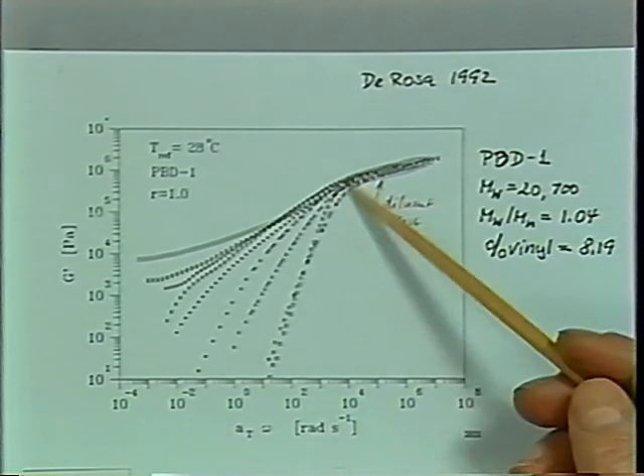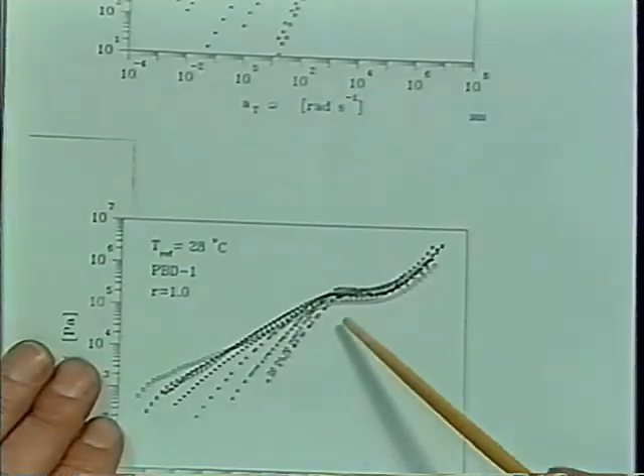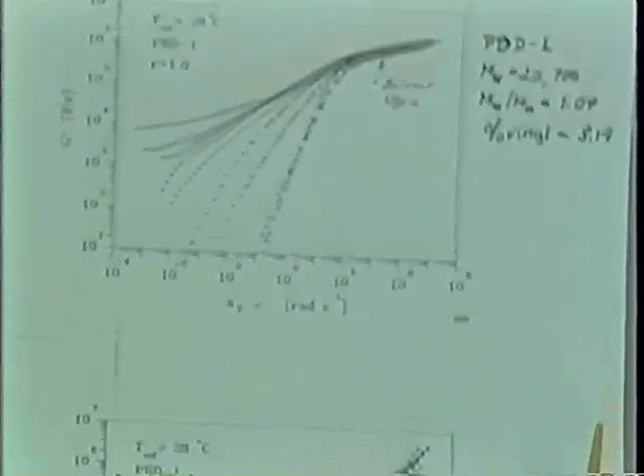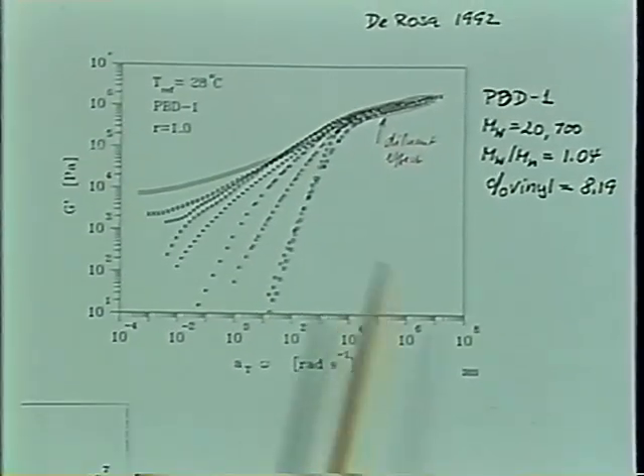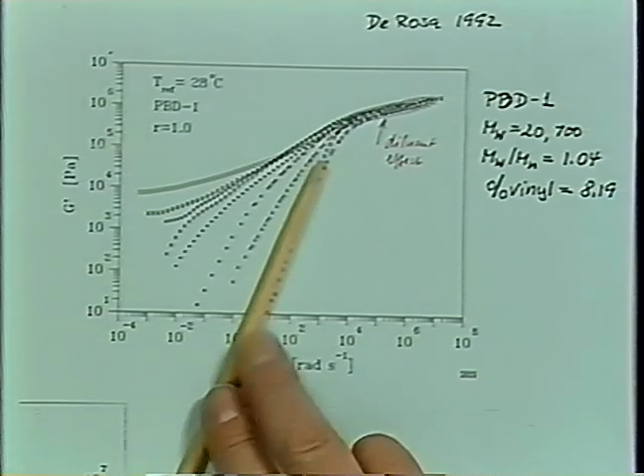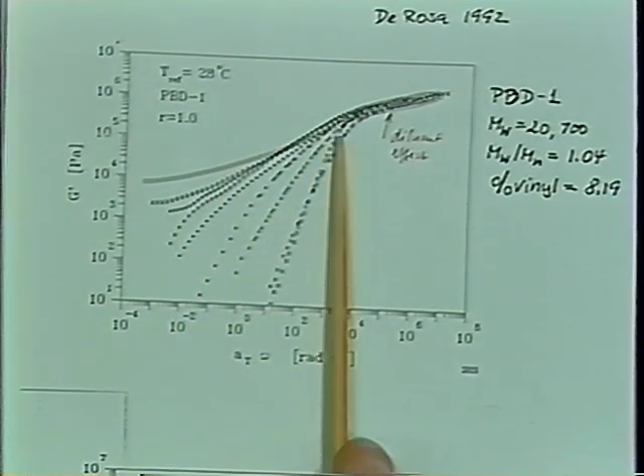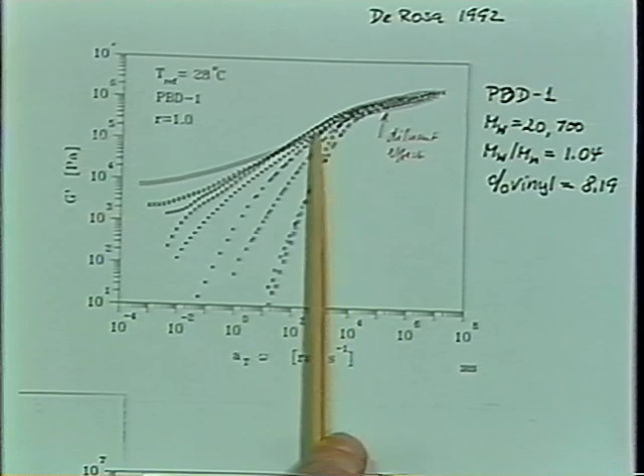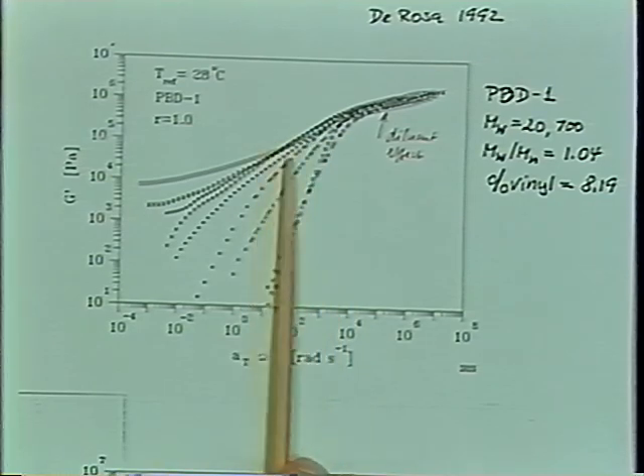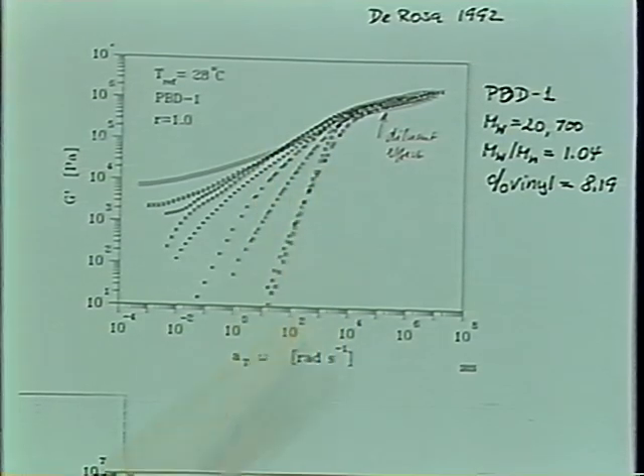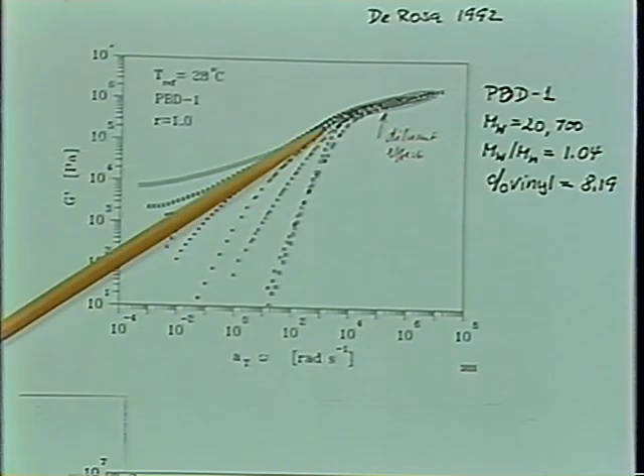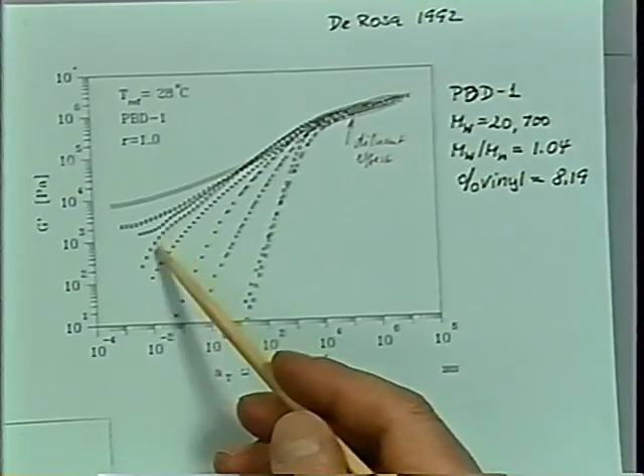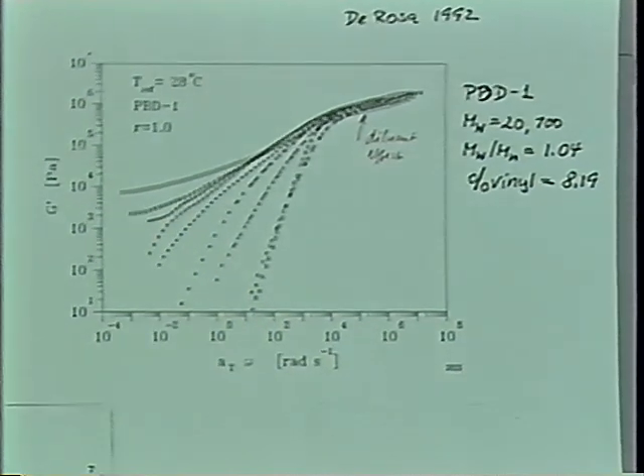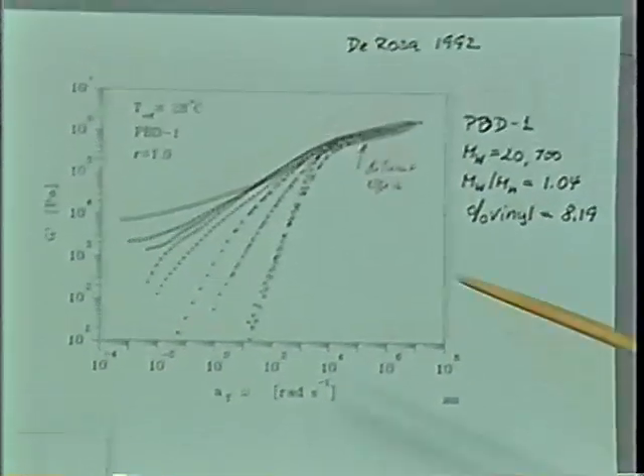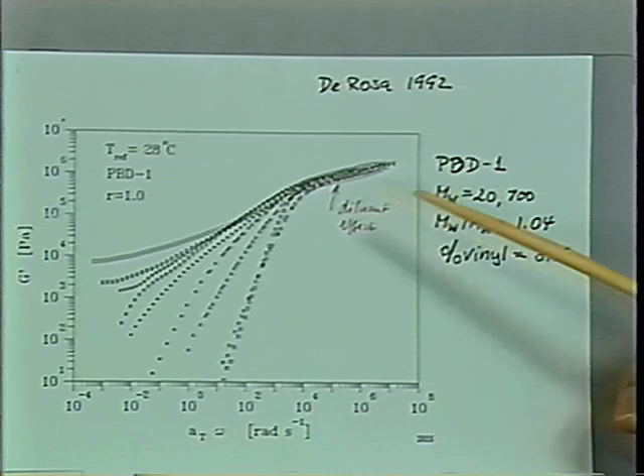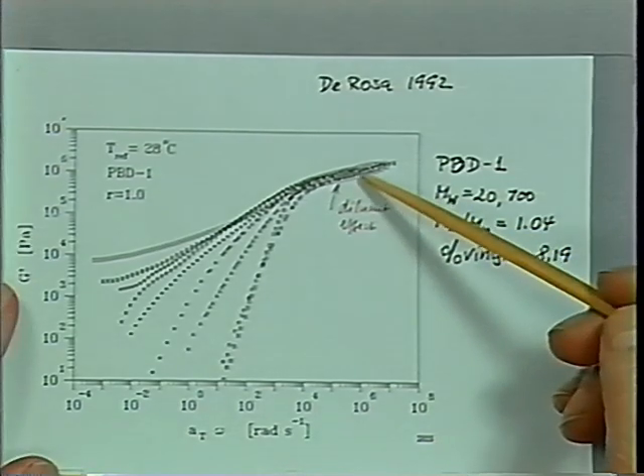The initial spectrum for G prime and for G double prime is shown again here. And then with increasing extent of reaction, the modulus increases. The longest relaxation time is increasing, so the terminal zone moves to lower frequencies. And then there's an intermediate state, a power state. Before that, the material is still a sol. Beyond that, it's a gel. There's some structure in the data which I should discuss.